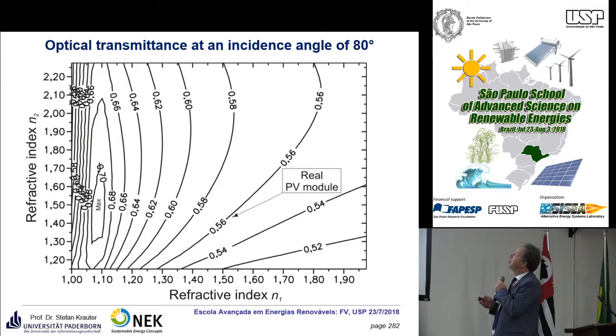It's more extreme if you go for an incidence angle of 80 degrees. If you have a model and there's a flat incidence angle, you have a higher reflection, so you're losing about 44% for a real PV model here. If you would really have a low refractive index in the first part, 1.1, you would gain a lot, about 25% more power, if you had such materials which would be able to reduce that reflection by this especially low refractive index.